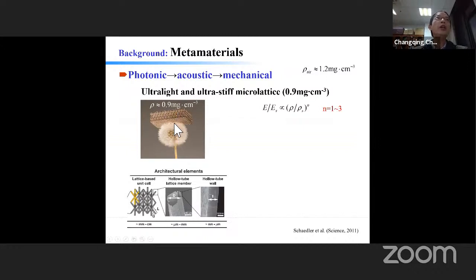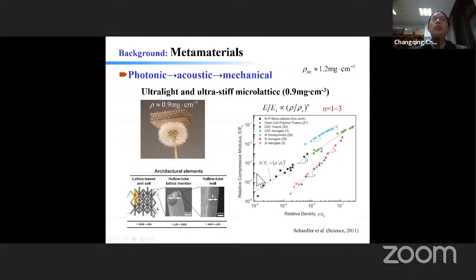The density of the micro-lattice is about 0.9 milligram per cubic centimeter, which you can see is, let's say, the density of air, which is about 1.2. The most interesting thing is if we look at the modulus here, the relative modulus of the material as a function of relative density.